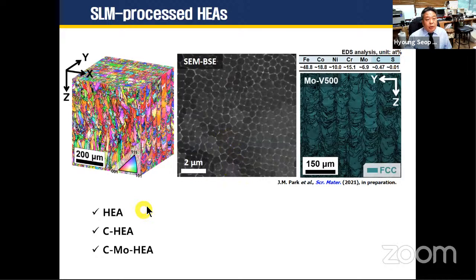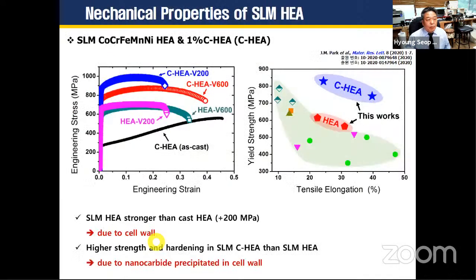So we prepared high entropy alloy and carbon-added high entropy alloys and carbon molybdenum-added high entropy alloys for playing with the cell structure engineering and segregation engineering. So this figure shows the stress strain curves with the various cobalt, chrome, Fe, nickel, manganese high entropy alloys. It's called Cantor alloy. The high entropy alloy and carbon-added high entropy alloy, just cast one, shows very typical low strength, in particular low yielding strength, and very high elongation, over 40–50%.